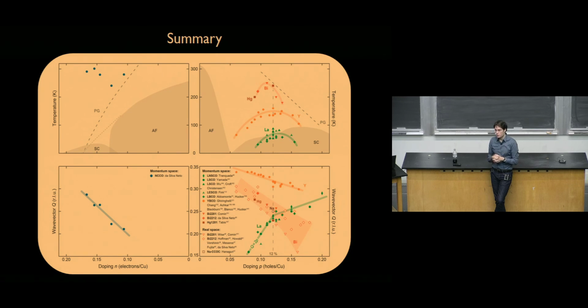So if there are pockets of charge order that are somehow disconnected and then supercurrents flow around them, then we cannot tell from our measurements, because we look at microscopic features by using macroscopic probes. But if we use nanoscopic probes, then we might be able to image single domains and really tell what the real space texture of charge order is and what the connectivity of that texture is. And that gives a lot of information on whether there is some kind of percolative regime expected to be reached at some point, or in certain cuprates, superconductivity is never fully suppressed, even in the regime where charge order is strongest, right? You have a dip in the TC, but it doesn't go to zero.